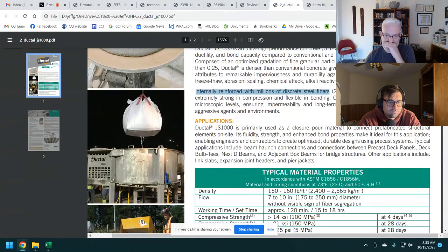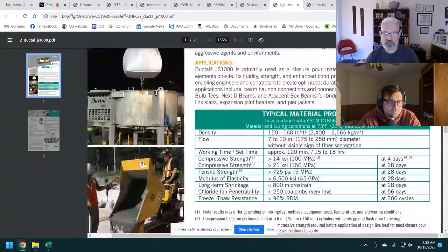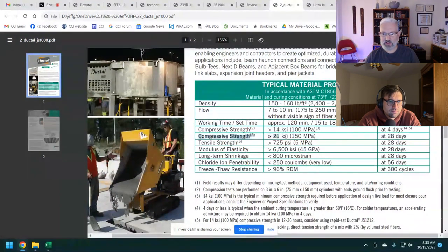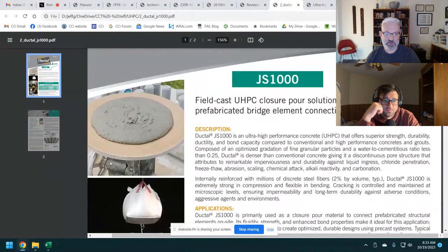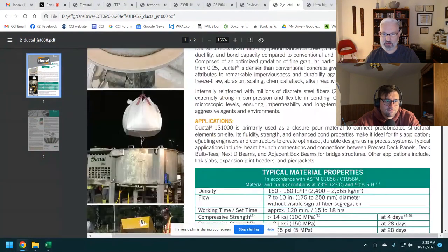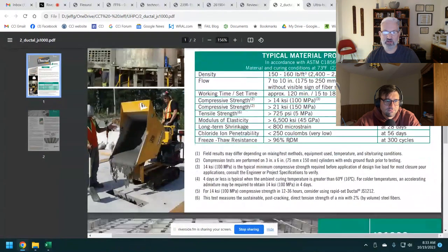Again, this is not a strict definition. I'm just showing you what the concept is. And here's your compressive strength, greater than... Interesting, by the way, the flow, 7 to 10 inches. That's fascinating given the flow conversation we had last week. That's a flow test right there, that little cone that I showed the other day. It happens to be on the machine where they don't turn the crank to make it go up and down, that's a different test. But yeah, 7 to 10 inches. A lot of the samples that I made, even with high fiber contents, have flows of greater than 7 inches, usually around 8 inches, which I consider moderate flow. And I showed you a 10-inch flow last week that I would consider a high flow.